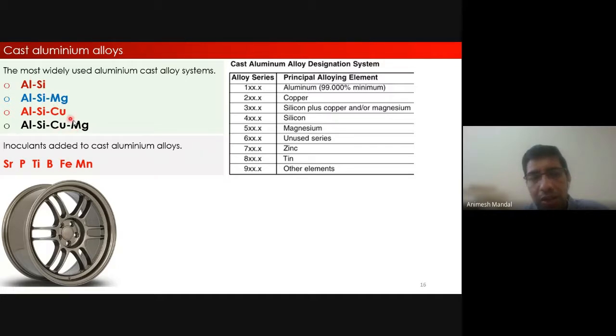So essentially, by adding these alloying elements, you're making a non-heat treatable alloy into a heat treatable alloy. And why is it so? Because you can increase the strength of these alloys by proper heat treatment. For example, the alloy wheels which you see in most cars nowadays are all made using aluminum alloys. Hardly any steels are used for making alloy wheels. It's mostly different grades of aluminum alloys. Of course, it's aluminum silicon base, but these compositions could vary here and there depending on the company, which company prefers which kind of composition, keeping the strength factor in mind.